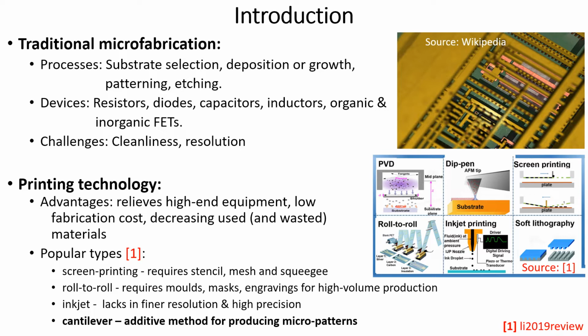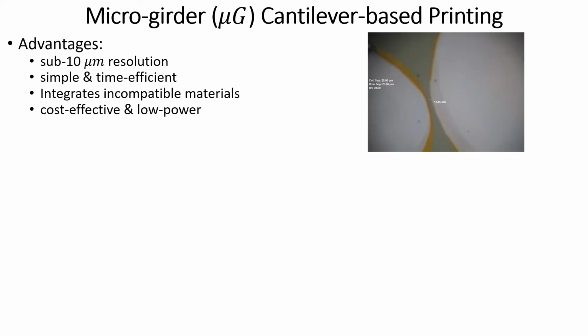The cantilever-based technique, which is used by us, is an additive technique to produce micropatterns having a feature size resolution of 0.5 to 1000 micrometer. We have created a novel variation of the cantilever technique called a microgirder variation. This technique is capable of producing patterns in the sub 10 micrometer range. In fact, we were successful in creating diodes with a spacing as low as 2 micrometer.